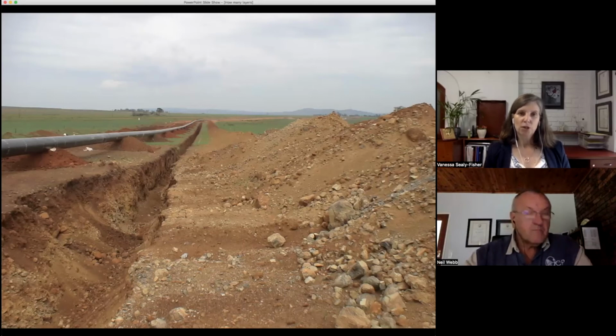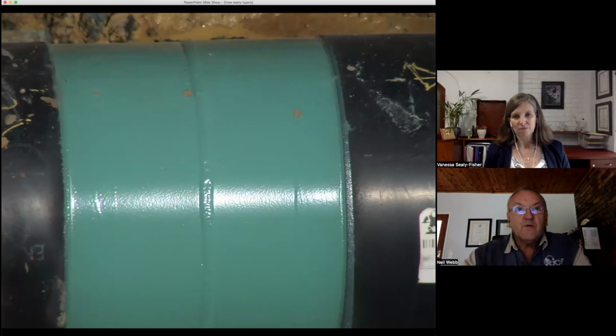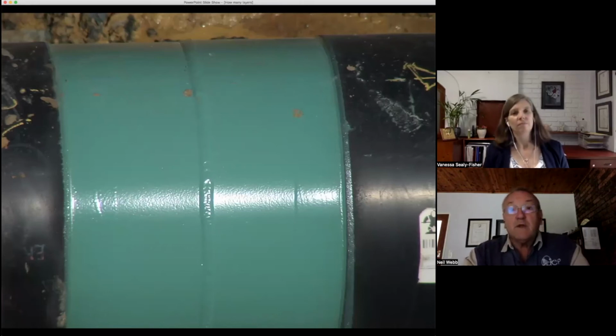The other concern that engineers, we shouldn't lose sight of is the bare bits of steel that still need to be joined together when we get our field joint coating. Yeah, well, we saw that end of a pipe a few slides back. And here's one of those pipes that's now been welded together. And you can see the epoxy toe sticking out from underneath polyethylene. And this particular joint has now been coated with a fusion bonded epoxy. It could have been a liquid epoxy.